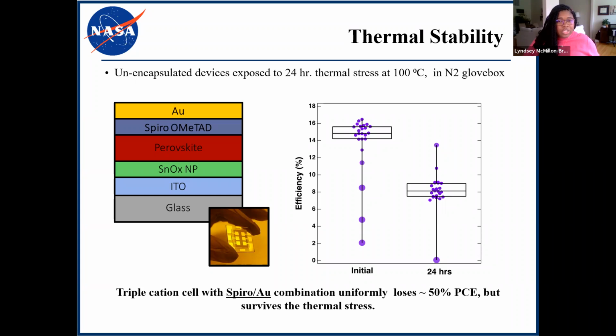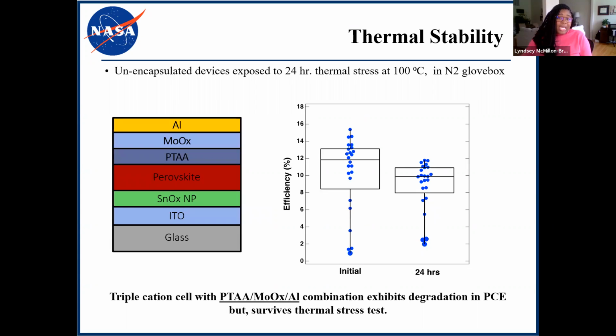And upon closer inspection, we realized that the short circuit current remained largely unchanged. The open circuit voltage dropped marginally from about 1.1 volts to 1 volt. And again, the greatest losses we observed were actually in our fill factor, and that's symbolic of reduced efficiency in extracting our charged carriers.